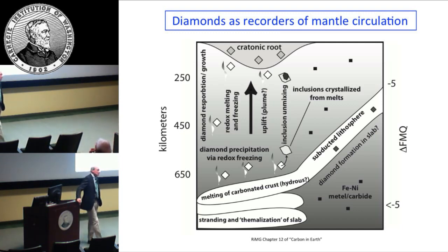Well, I don't think that's an in situ thing. I think the grain grew, and I think the diamond must have had a crack in it. Sometimes these cracks are difficult to see, or they're healed, and when you do this kind of work, you look very carefully. Steve and I were looking at a grain yesterday from a Letseng diamond, and we thought we had everything perfect, but then there's a little place where the fracture system intersects the surface. And if you've got any of that going on, you have pressures and temperatures where then you're suspect. You're worried. And we didn't like the color. It didn't look brassy. It didn't look like a sulfide. It looked black. I'd never seen that before. Although the sulfides usually fracture the diamond from within.